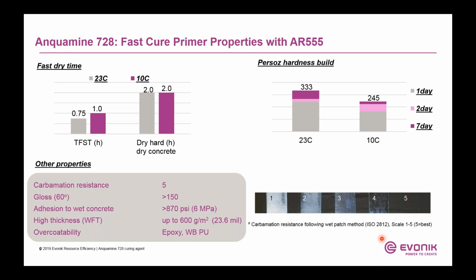So carbamation is a test of amine salt formation on the coating surface. If there's any residual unreacted amine that migrates to the surface, then it will react with moisture and carbon dioxide in the air to form carbamate salt. And then the salt will show up as white. So on the scale, 1 is worst, a lot of salt formation, and 5 is excellent, no obvious salt formation.